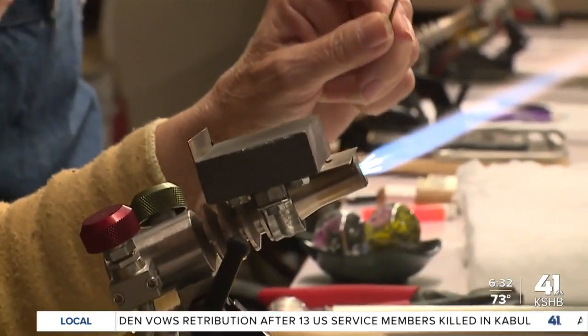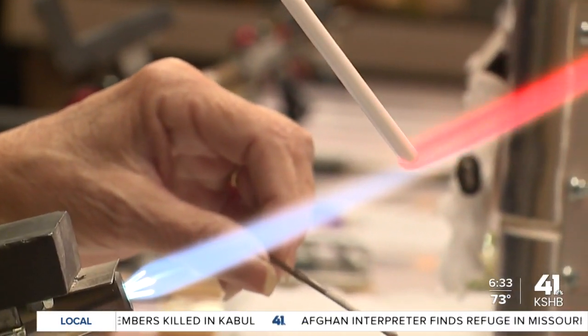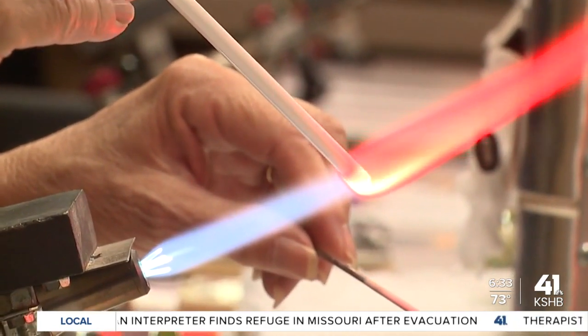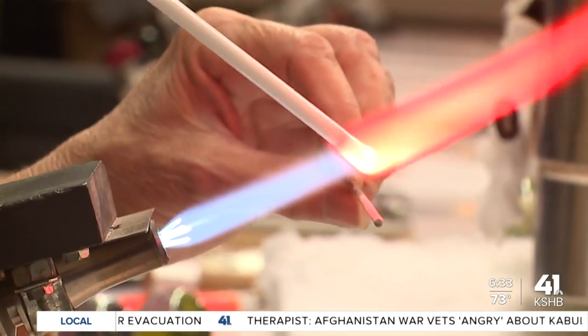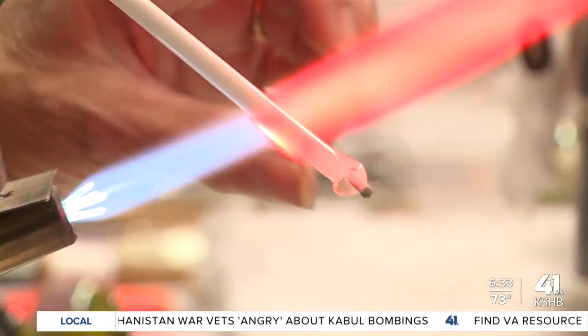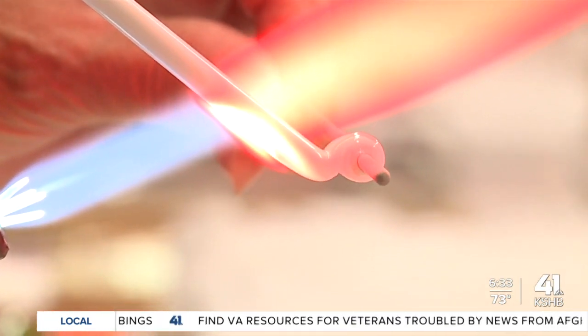You're going to warm up just the end of this thing called a mandrel. It's been dipped in a graphite solution so that when you put the glass on there, the bead won't stick. Take the glass and point it down towards Canada, and once it stops popping, you come down to Kansas. You gather a glob of glass — bright orange — touch it to the mandrel, and then very slowly twist away from yourself. The bead should be slightly below the flame.